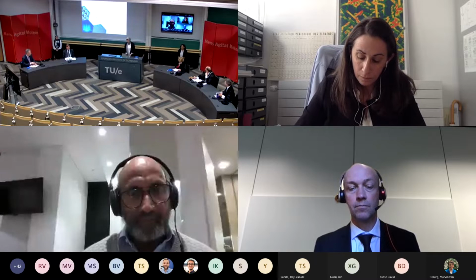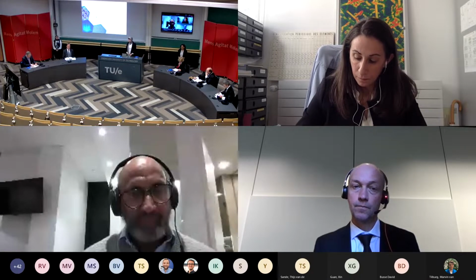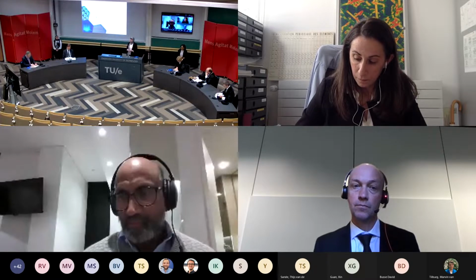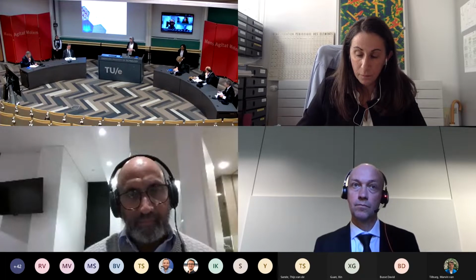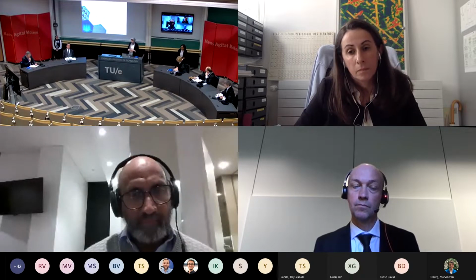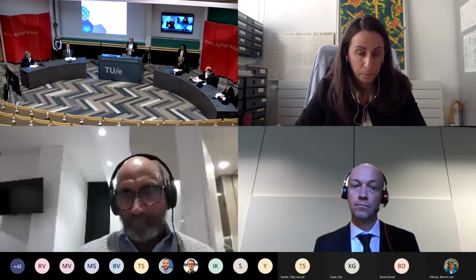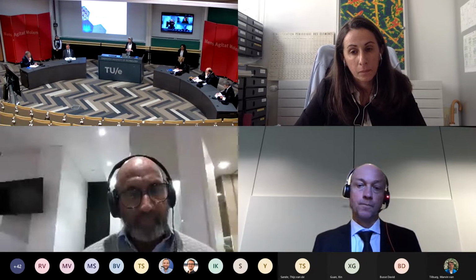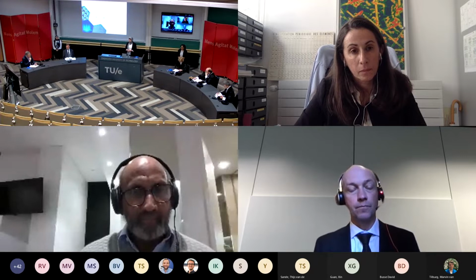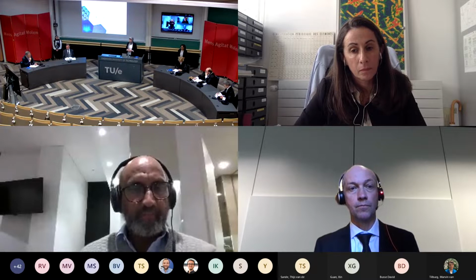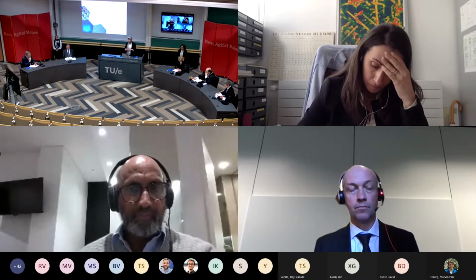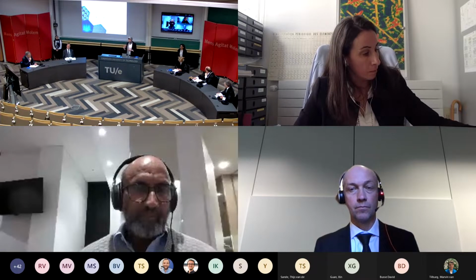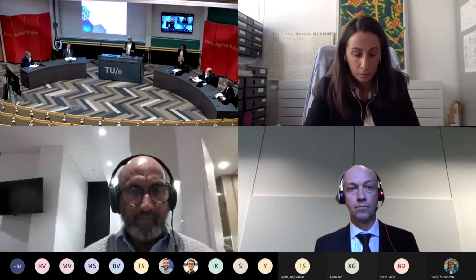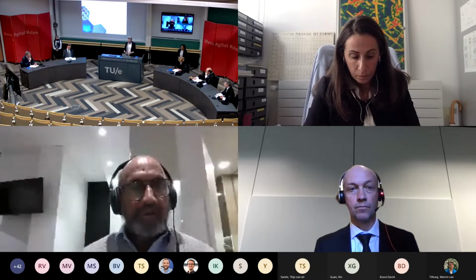Dear opponent, thank you so much for the question. We do that by optical characterization methods. We used photoluminescence to determine the directness of the band gap of the material. My colleagues in the team did the optical characterization, and they did a series of measurements. First, they made a power dependent series, monitoring the optical emission of our nanowires as a function of power. We also did a temperature dependent series to see the evolution of our emission. By comparing the different results we got, we could tell the behavior that shows an indirect versus a direct band gap material. Do you want me to dig deeper into details?